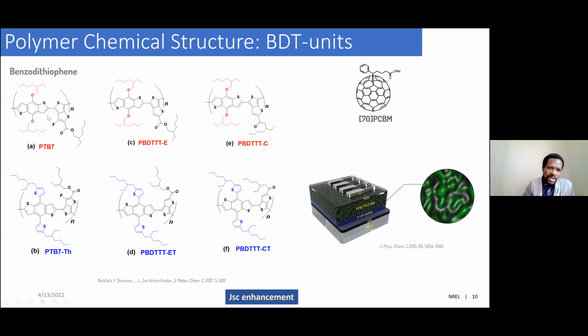So if you pay real attention, the change is only happening on the side chain. So this first one, the counterpart is B. You can see the only change is on the side chain, and you can also compare these two. Another strategy used by the community to increase efficiency is the use of additives in the active layer. One particular such additive is DIO (1,8-diiodooctane), which has become popular in the field. All these tricks have been used to increase the efficiency.